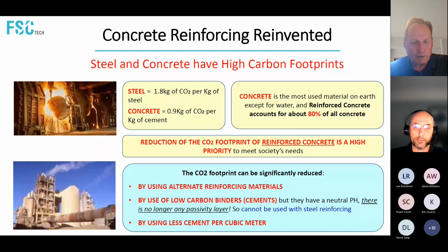One is you can use a different kind of reinforcing material, which is what we're exploring. The second is by use of low carbon binders. And these have been invented for decades. They've been around for a long time. But the issue is they have a neutral pH. So you no longer have that passivity layer helping you protect it. So it has had a very slow uptake in anything where steel reinforcement structural concrete is in play.